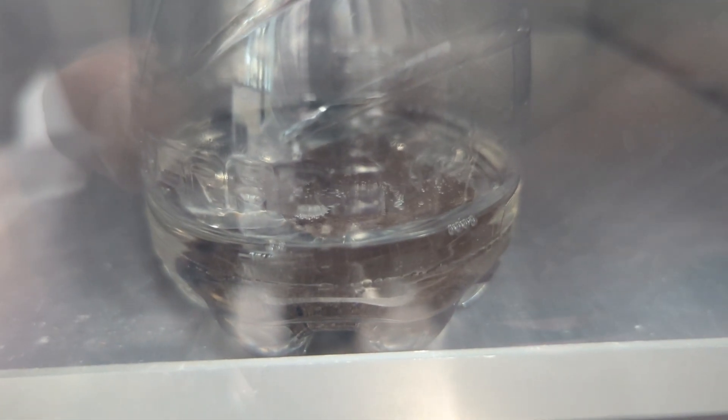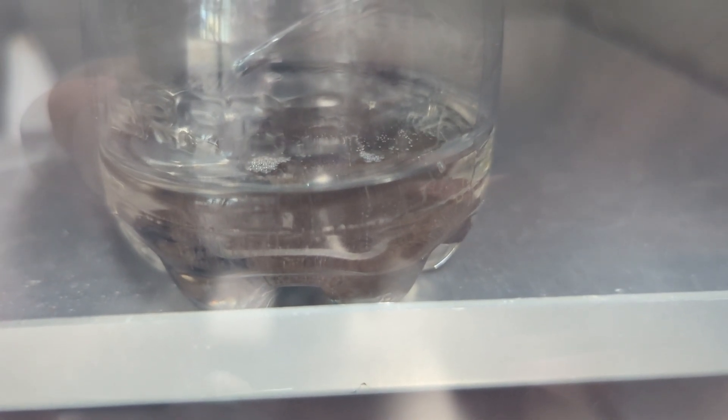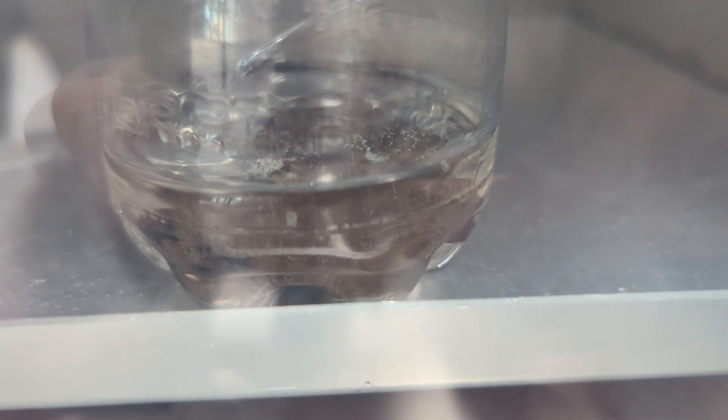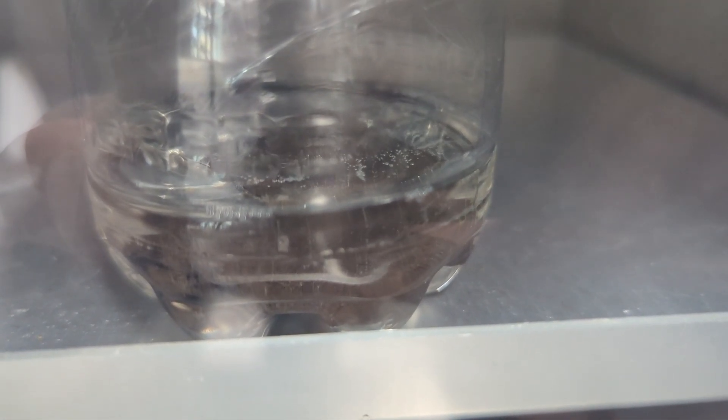So even this when you do it you're going to see a huge amount of bubbles. Depending on how porous your material is the bubbles are going to be pretty aggressive. Make sure we've got enough room just in case you get any spillover. But this is a pretty low solvent kind of material. So you're not going to get a huge amount of gas forming and overflow your container. You'll just see it's basically fizzing away like a soft drink. And eventually that's going to stop. Now don't be surprised if it takes more than an hour at a pretty low vacuum to be able to stop.